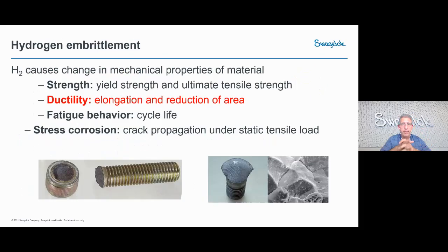So that leads us to hydrogen embrittlement. This is another form of environmentally induced corrosion or cracking. There are a lot of materials in which hydrogen, being one of the smallest atoms as well as one of the most prevalent materials in the environment, can readily get into materials and really impact the atomic bond strengths between the atoms in their periodic arrangement. As you can see in these pictures on this slide, these failures show no noticeable observations of a lot of plastic deformation to the parts prior to failure.